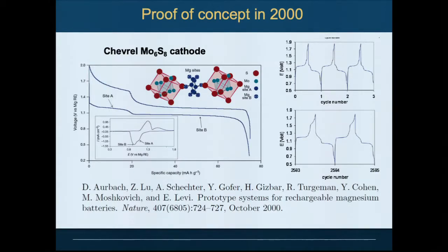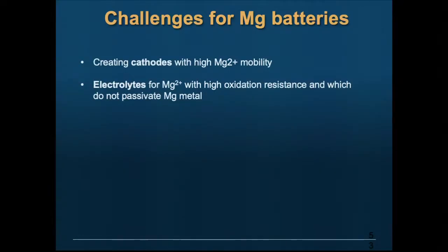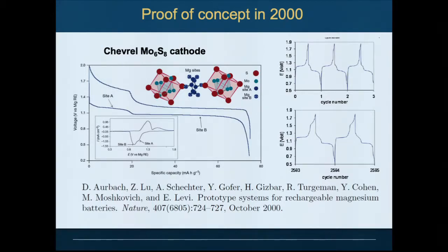So what's the challenge? There are essentially two challenges, right? You need cathodes with very high magnesium 2+ mobility. And that's hard, right? You now have a divalent ion that polarizes its environment a lot, so it's going to be much harder to move. And you need electrolytes that can run magnesium without passivating magnesium metal. Because if we passivate magnesium metal, the game's over. Magnesium oxide is impenetrable. Proof of concept was done already back in 2000 by Doron Aurbach in Israel, who showed a working magnesium battery with a Chevrel sulfide cathode. This is remarkable. It runs at room temperature, but the voltage is low, the capacity is low, but it is a proof of concept.